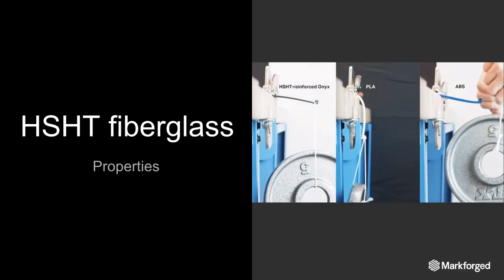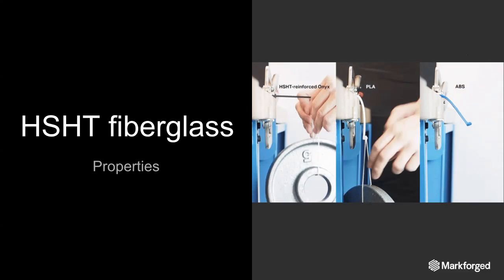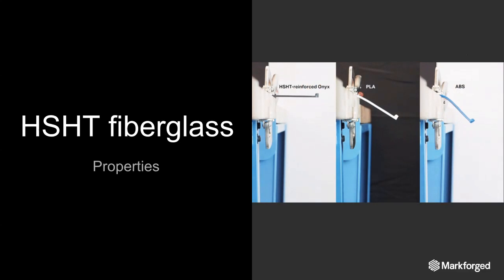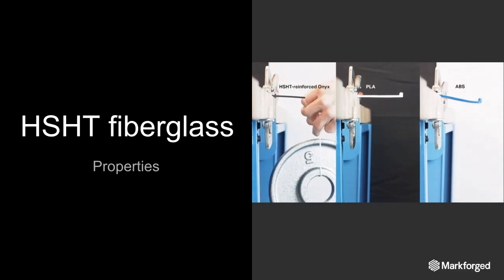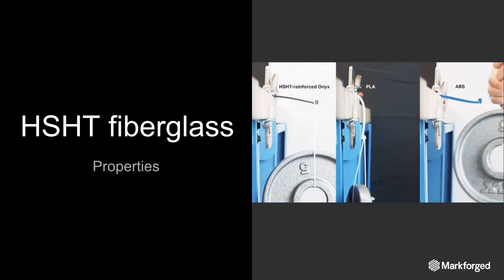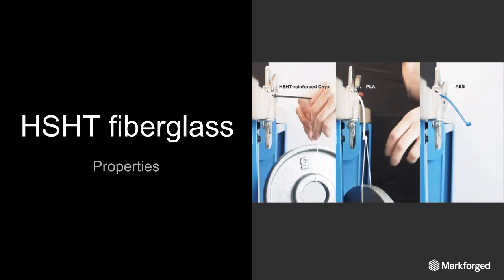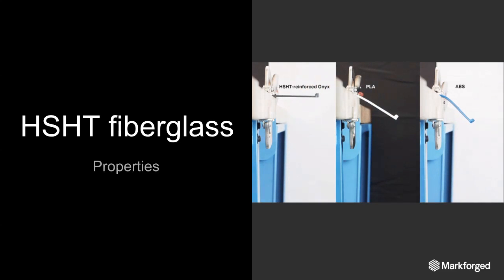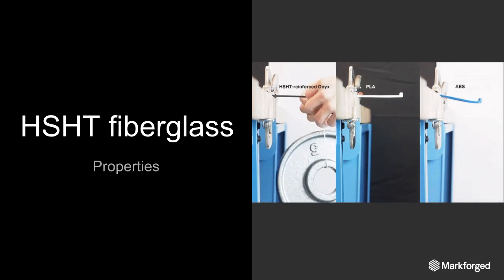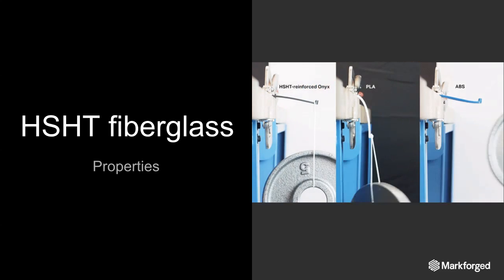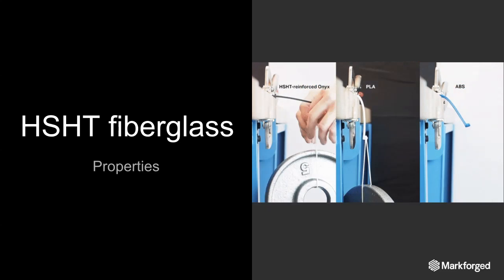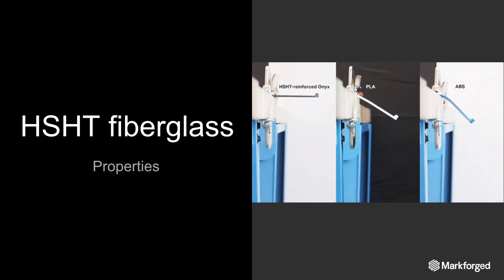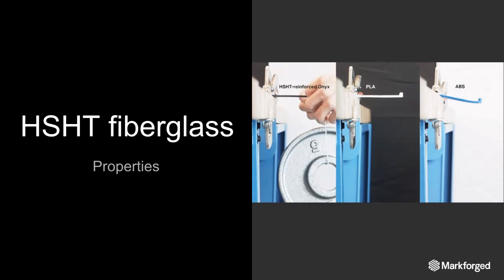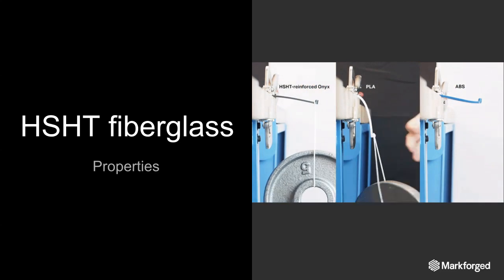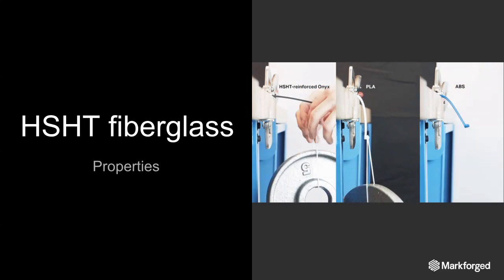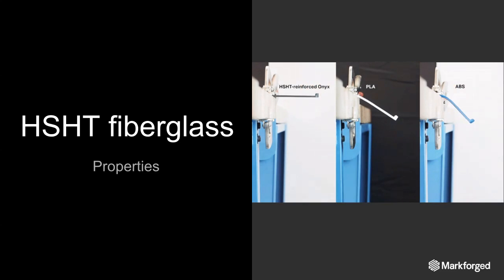So before this video was shot, each of these beams was heated in an oven at 140 degrees Celsius, which is about 285 Fahrenheit. The HSHT reinforced beam retained its strength and stiffness, as you can see, and it was able to support 5 pounds hung from the end while deflecting a little bit, whereas PLA and ABS actually started to deflect under their own weight before the weight was even hung from the end. And then you can see they basically were pretty limp as we put the weight on.